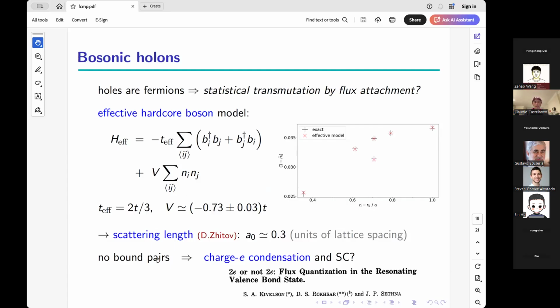nearest neighbor interaction. Interestingly, Daniil then went on to do some field theoretic calculations, some ladder calculations, to get the scattering length in units of the lattice spacing, 0.3, and this suggests that there is no binding, and therefore condensation of these holons as bosons is possible, and that would lead to some kind of charge-2e superconducting transport phenomena, which would be exotic and interesting to explore. It relates to an old dilemma that was discussed by many people, among which Steve Kivelson in one of the perhaps nicest PRL titles I'm aware of, 2e or not 2e, flux quantization in the resonating valence bond state.